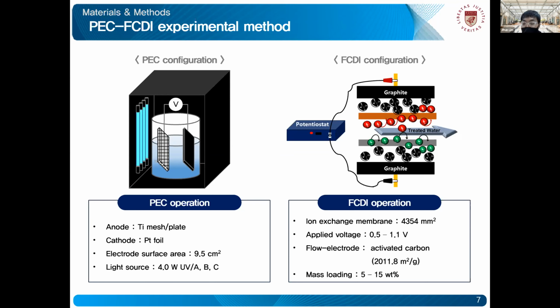For the flow electrode, we used activated carbon with a BET of approximately 2000, and the mass loading of the activated carbon was between 5 to 15 weight percent. If we increase the mass loading of the activated carbon within the FCDI system, the overall performance of the process would obviously increase. However, studies in the past have shown that if we increase the mass loading above 20%, the solution leads to clogging of the system because the viscosity becomes much too high. So in our work, we limited the mass loading to 15%.